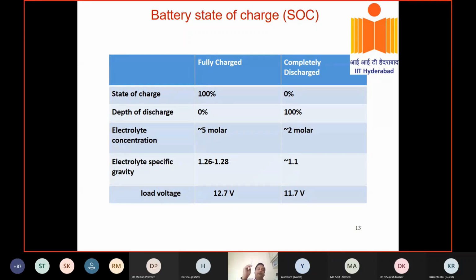So in real life, if it is 100% charged, that means the state of charge is 100%. What do you mean by state of charge? It is the capacity at any instant to the total available capacity. The capacity at any instant to the total available capacity is called state of charge. So that means when it is 100% state of charge, the depth of discharge is 0%. The electrolyte concentration is around 5 molar, which means a specific gravity of 1.26 to 1.28. And then the load voltage is around 2.1 volts per cell. So it is fully charged.